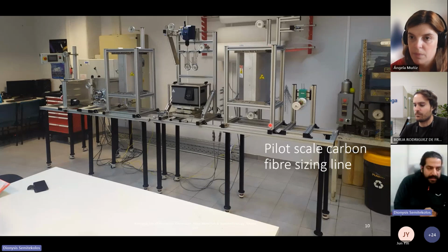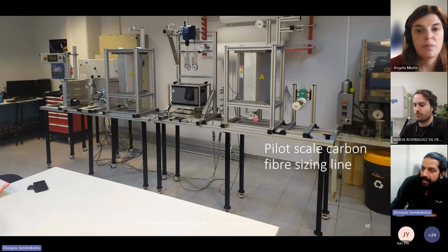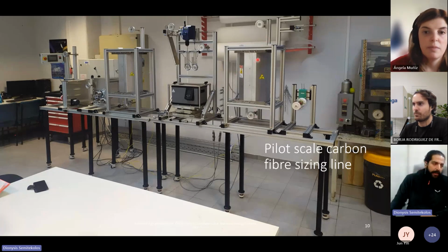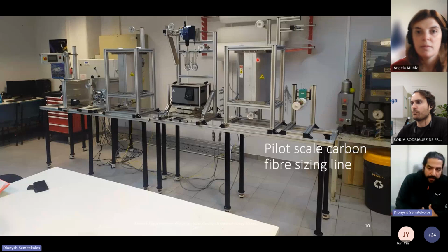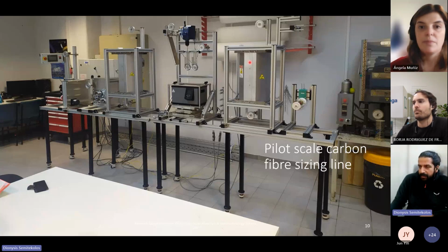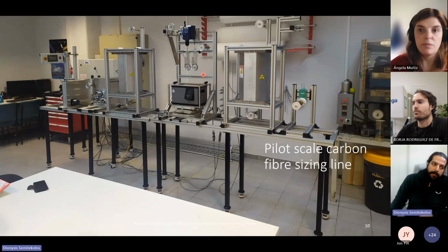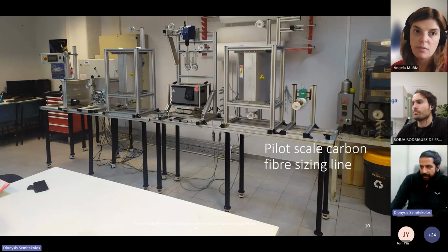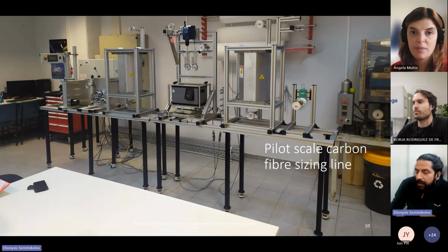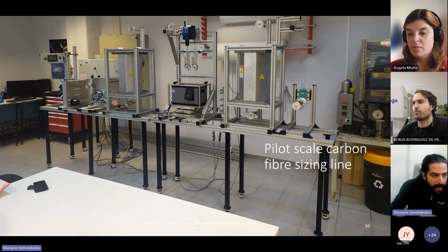If it contains excess resin, then we need to remove this by applying heat on the fibers. If they are clear from residues, we don't need to activate this. Then we have this bath where the fiber gets impregnated, and through this nip roller, the excess is squeezed out and returned back into the bath. Then we have the second furnace where we do the drying of the fiber. We evaporate the solvent and we consolidate the sizing material, the solids.